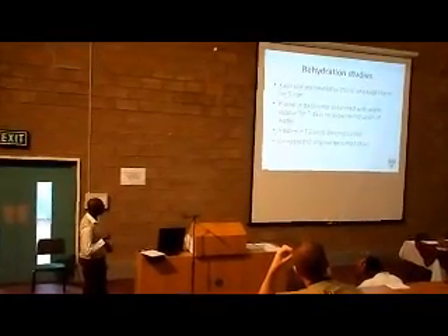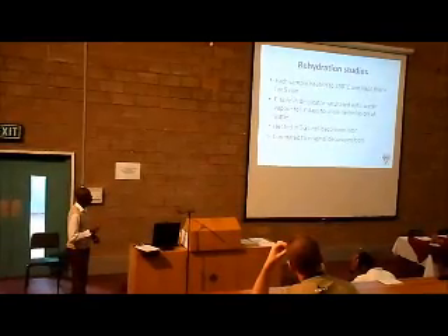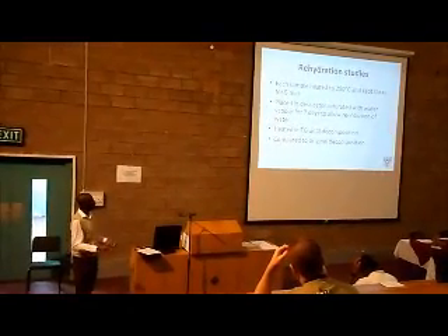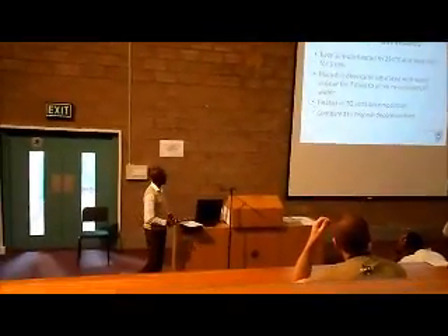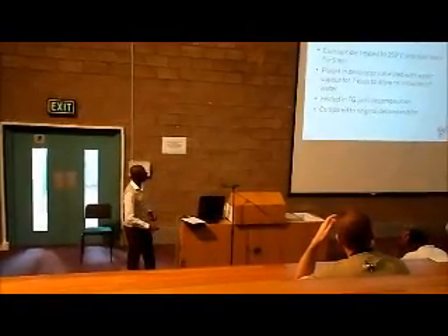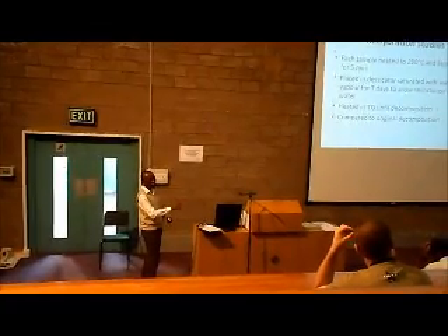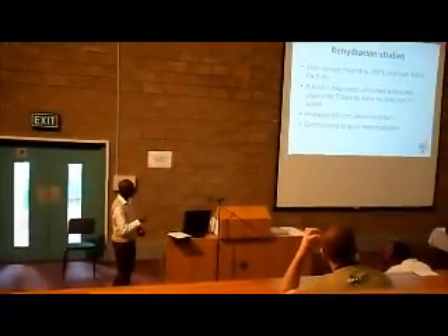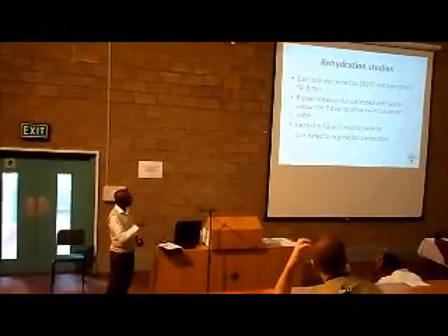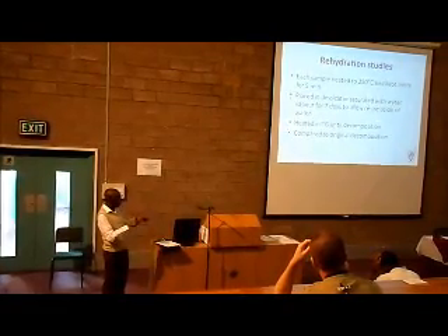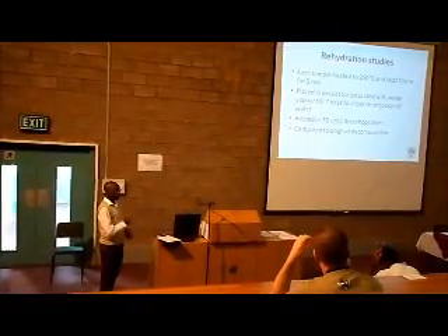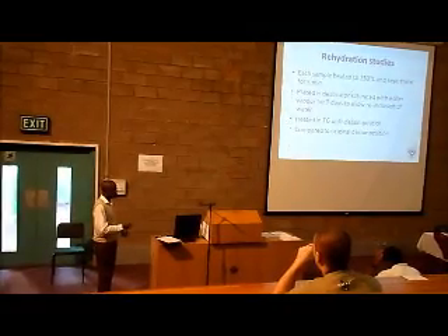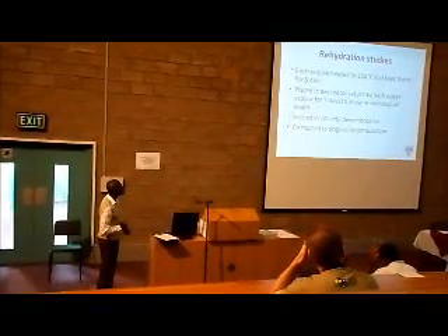They were then placed in a desiccator saturated with water vapor for 7 days to allow the re-inclusion of the water into the structure. And then they were heated again in the TG until decomposition had been achieved, and this was roughly at around 600 to 650 degrees. And then we compared this rehydration decomposition to the original decomposition, which was done before we did the rehydration studies.